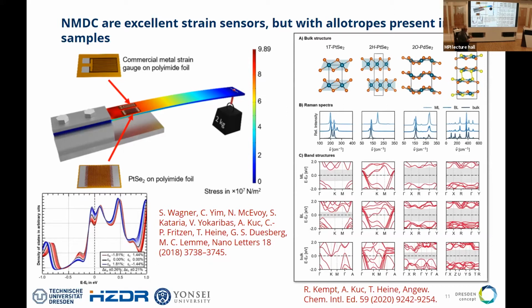There are a lot of allotropes. The allotropes are very close in energy, and so here the 2 left columns are on platinum diselenide. You can see here 2 different phases. They look very similar for a physicist maybe, but if you look at the chemistry, they're quite different, and they have very different electronic structures from metal to semiconducting, and also the number of layers gives you very different band structures. That means that's the reason why it's hard in an experiment to get these structures. You have to be very, very careful in working on that. But of course, we have very good experimental colleagues, and they have that under control.